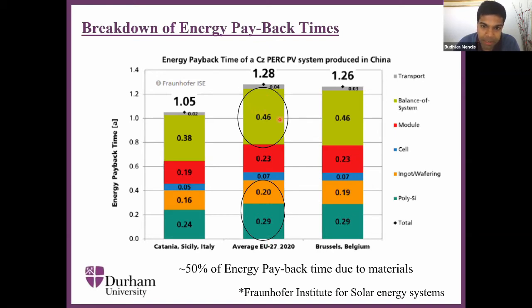So if we break down the energy payback time, what you see is that the major contributors are this contribution called balance of system. This is typically the inverter that is used for converting DC into an alternating current. But at 50%, another large percent is taken up by the materials cost. So the cost of producing silicon from sand, as well as shaping it into the required wafers. So if we can reduce the material cost, in other words, if we could replace silicon with materials that are more strongly light absorbing, then potentially we have huge energy savings that we can introduce, thus making silicon solar electricity a lot more attractive.